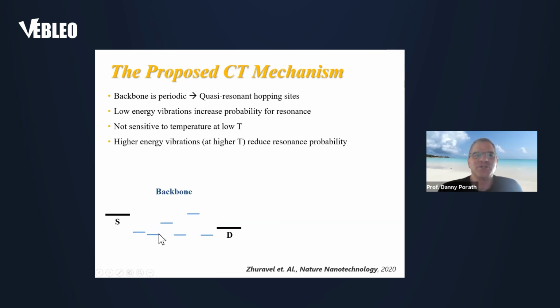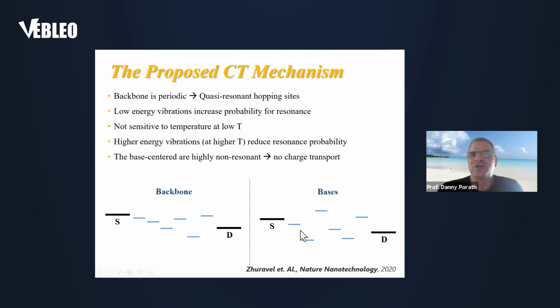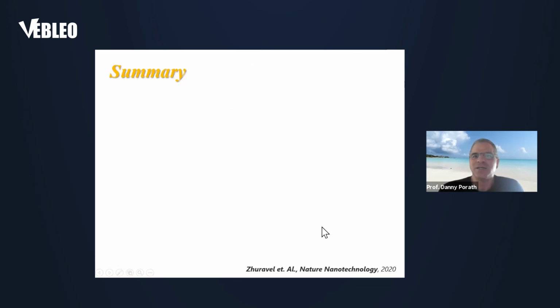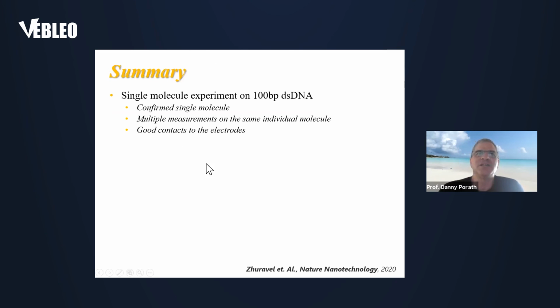And at higher temperatures, there are vibrations, and they cause the reduction of the current, because the resonance is not as good as before. When we compare to the base states, so in the case of the random sequence, the bases are not aligned and they kind of flicker. So then there is much less possibility for such a resonance, and then we don't have the current through the bases. So that's kind of explaining the experimental behavior that we see.